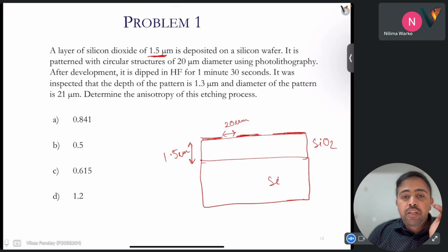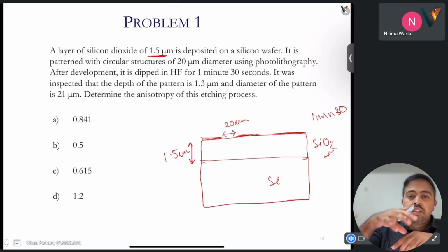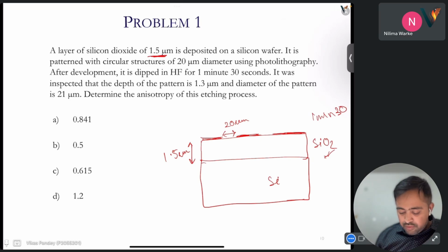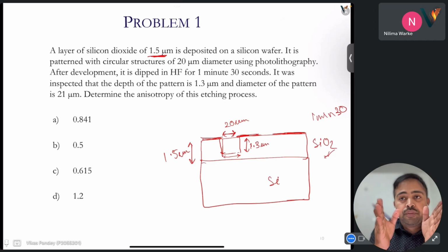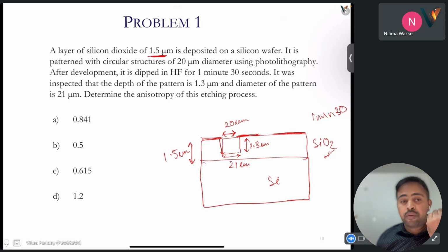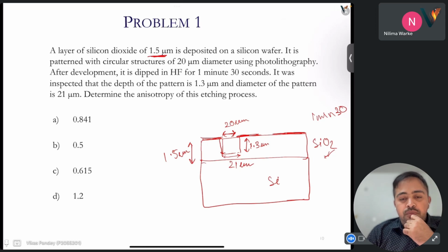After development, it is dipped in HF for 1 minute 30 seconds. After it was dipped in HF, that will remove SiO2 for 1 minute 30 seconds. It is found that the depth, we are finding the depth till here, is 1.3 micrometer. So it has not reached the end yet. And what was expected was a 20 micrometer pattern, but we got 21 micrometer. What is the anisotropy of this etching process?